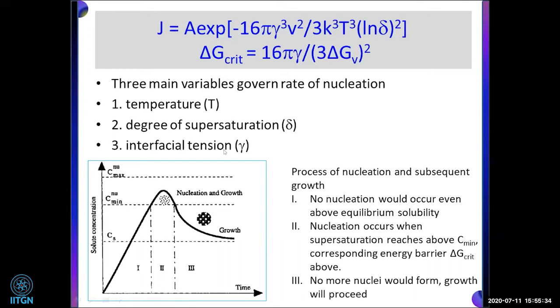That means if we increase the temperature of the reaction, we increase the rate of nucleation. If we increase the supersaturation, which is the concentration of the precursor, again we are increasing the rate of nucleation, you can see in this figure. And if we reduce the interfacial tension, through the use of a surfactant, then again we are increasing the rate of nucleation.